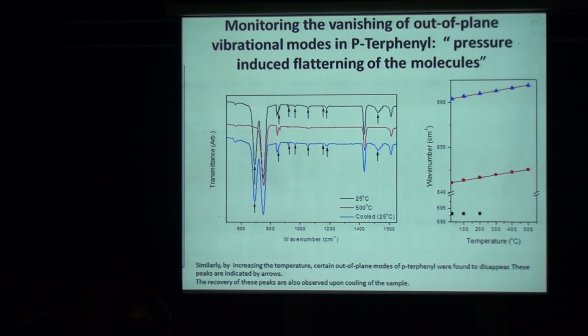We do not have to worry about all these peaks. You just see that initially at 25 degrees Celsius, we can track the vibrational modes of what we call the biphenyl molecule, the twisted phenyl ring. The moment we heat it up to 500 degrees Celsius, the peak did not disappear until 500 degrees Celsius. Then you see immediately that this peak disappears. And then if you cool it down back to 25 degrees Celsius, it comes back up. So the process is dynamic. Using this chemical molecule, we have biphenyl, triphenyl, tertiary phenyl. The longer this molecule, the harder to bend all the rings back in plane. Then we perform a theoretical calculation to know what pressure is needed to bend it in plane. We can calibrate the temperature and pressure relationship.